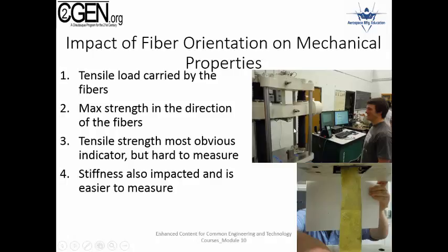So you're looking at load applied, force applied, versus stretch or strain, deformation, if you will, of the specimen. And you can see here, this is a specimen that's been stressed to failure. You see it's starting to break fibers up here in these portions. So that would be a great way for us to relate fiber orientation or ply placement to mechanical properties. But it's expensive. So we wanted something that was less expensive so that we could do on a casual basis.